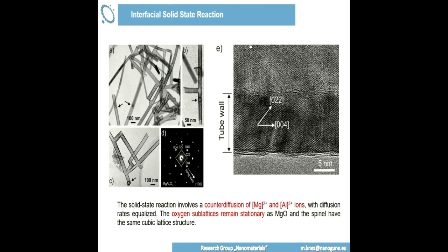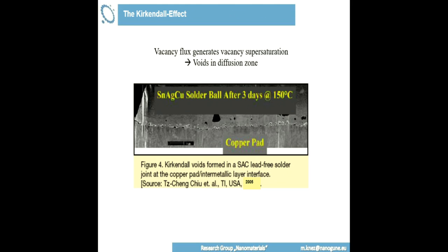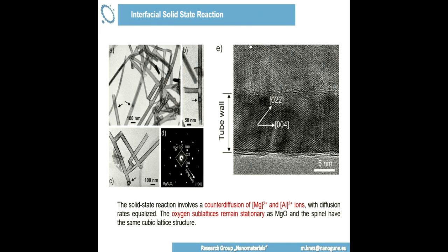And it was equal because you had magnesium and aluminum ions, which counter-diffused into the same lattices. That means you had a stationary system of oxygen which preserved the speed of the diffusion of the ions. At the end, you had an exchange 1-to-1, basically, or charge balanced 1-to-1. But this works in many systems as such.